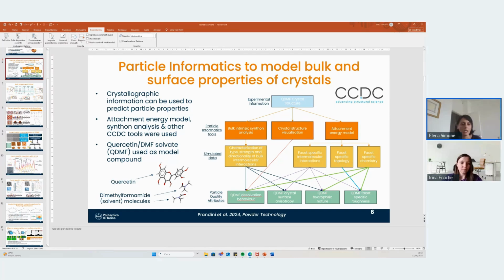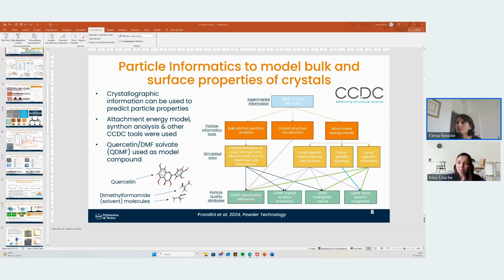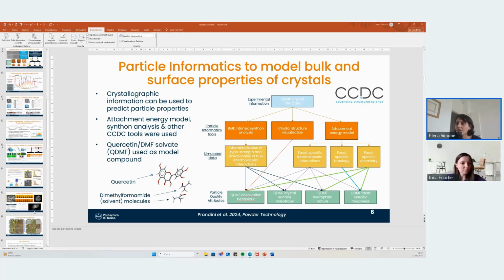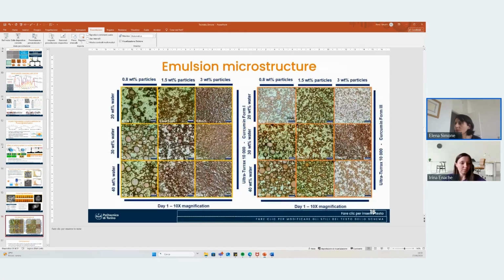So the covering really depends. There are other cases, maybe I can show you another picture. I don't know if I'm still sharing my screen, but there are other cases where larger droplets are a lot less covered. So for example, these ones here. With fewer particles, especially with a high amount of water, you see lower coverage. But then those might be a little bit less stable because they will tend to coalesce a lot more.